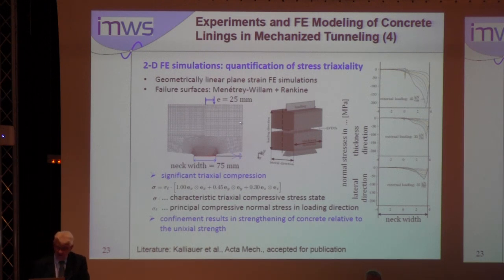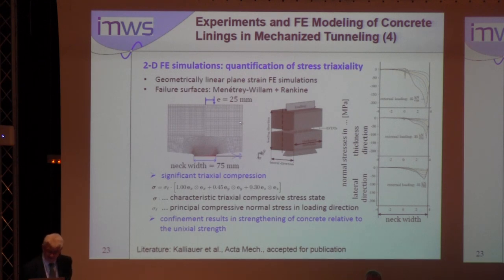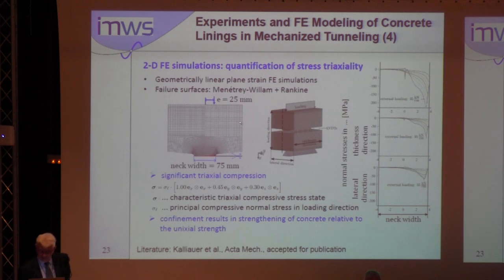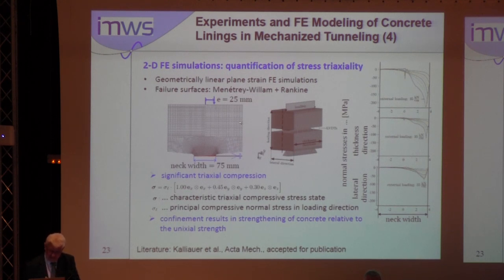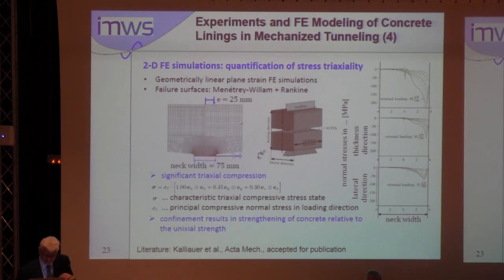For the 2D finite element simulations to quantify stress triaxiality, we carried out geometrically linear plane strain finite element simulations with failure surfaces by Menetrey-Willam plus Rankine for tension. The figures on the right show normal stresses along the neck width: for the loading direction at top, the thickness direction in the middle, and the lateral direction at the lower end. If the stress level is 1 in the loading direction (compression), it is 0.45 in the thickness direction and 0.3 in the lateral direction — a triaxial compressive stress state in three directions, needed for concrete hinges, resulting in strengthening relative to the uniaxial strength.